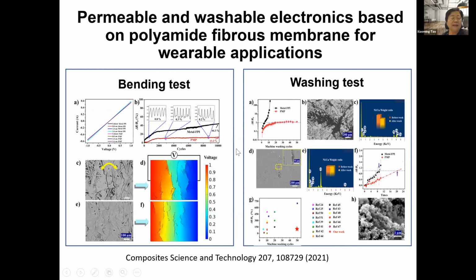And then what about the bending? They can bend up to 10,000 cycles. And there are some changes in the electrical resistance. Okay, and with these bending tests, but they are much lower than the others. Okay, this is about the conductive tracks. And what about the washability? They have excellent washability, up to 50 machine washing cycles. They still stay very good, with close to no change in the resistance. So that is robust.